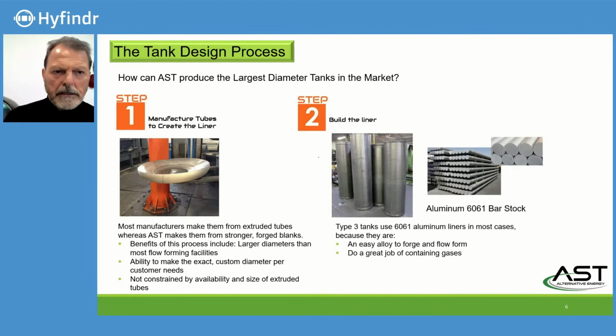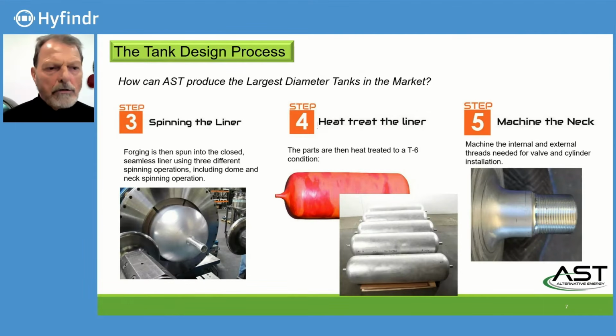But I think it must be hard to manufacture or to make these aluminum shapes and all these composites. Can you say how you do that? Yeah, so it's a different process than making a liner out of a tube. By forging, we get very large diameters, which is our focus, to get diameters over the dimension that you normally buy in extruded pipes. Therefore, we start with the forging, as you can see on the left slide. The forging is more like a dish, and then we start spin forming after that, and flow forming. It's made of aluminum stock of 6061. So we start with the 6061 billet, and go into the tube shape at the end. The next pass is then closing the tube at the ends.